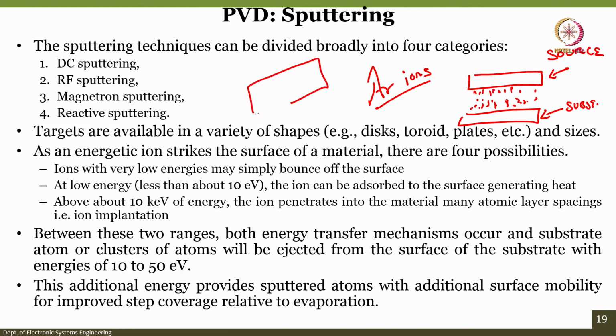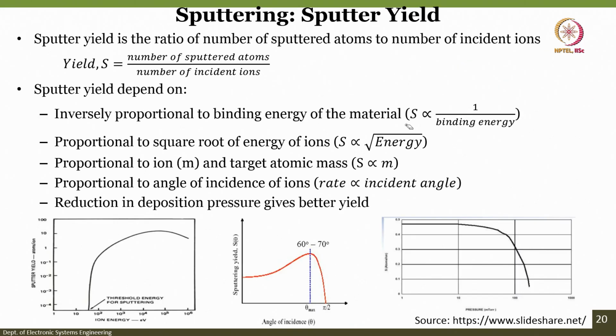Now, the advantage of this, because it is a dislodging of atoms and not really evaporation: if I have a step, let us say a step like this, the bombardment will occur uniformly everywhere. So, compared to thermal evaporation, where the step was not covered uniformly, the chances of better step coverage are higher when we go for sputtering. So, sputtering has an advantage over thermal evaporation, in that we can have better step coverage, okay. So, let us go to the next slide.